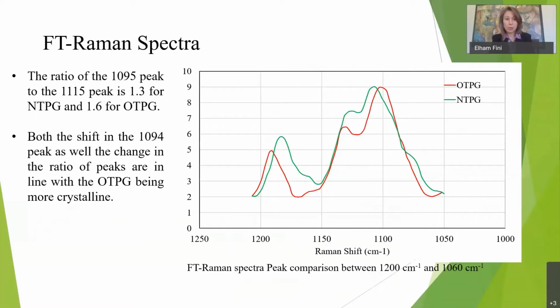Here is the Raman spectra, which we got with the help of Thermo Fisher colleagues. They helped us get some of this data and analyze it. Of course, they are on the co-authorship of the paper as well. So this one, the ratio of the 1095 peak to 1115 is 1.3 for non-treated and 1.6 for oil treated. So you can see the increase here. And they also have a shift in this, which is another indication of crystalline structure.